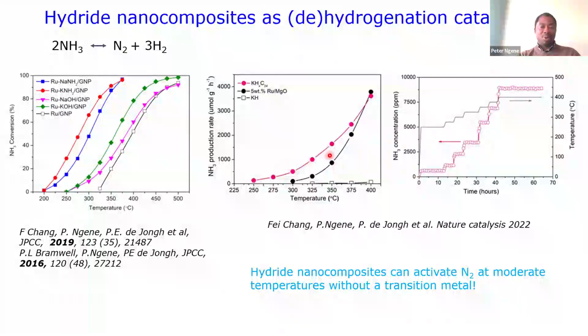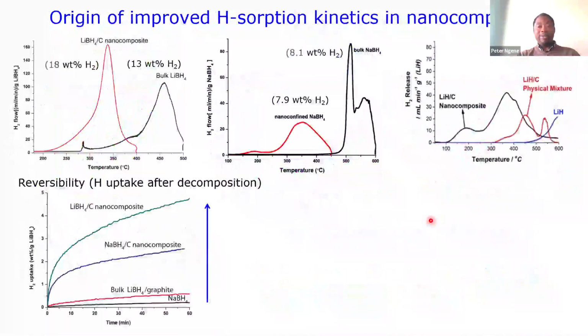And this makes it at much lower temperature. Which means that we have the first transition metal-free catalyst that can actually make ammonia at moderate temperature. And these materials are, you can see here, very, very stable. We can go up to 70 hours and we have stable ammonia conversion. So these materials are very interesting, and that's actually what I want to convince you about.